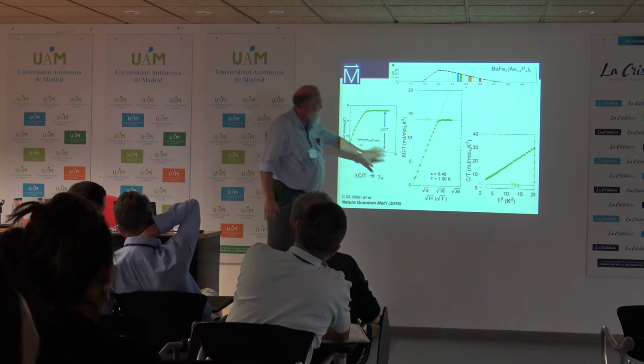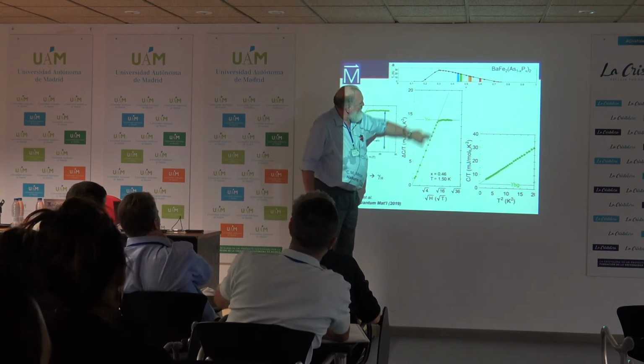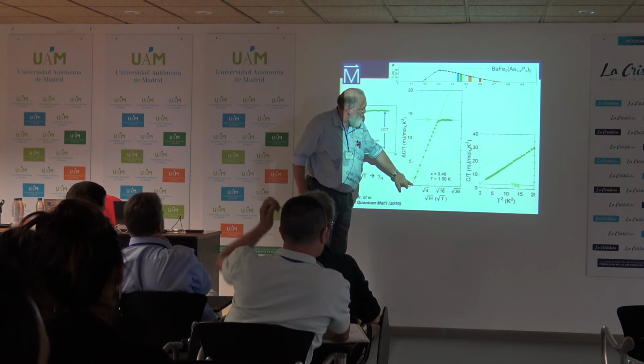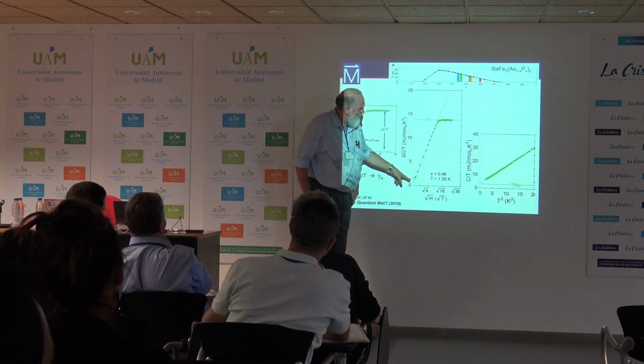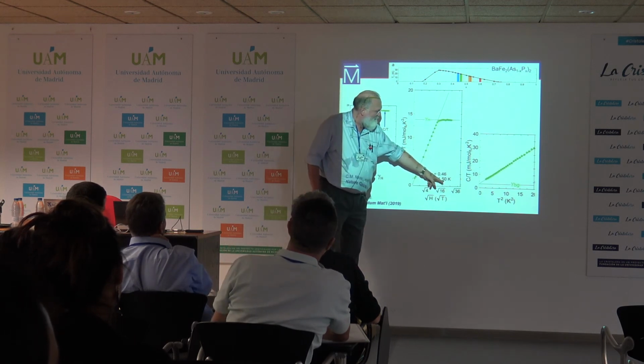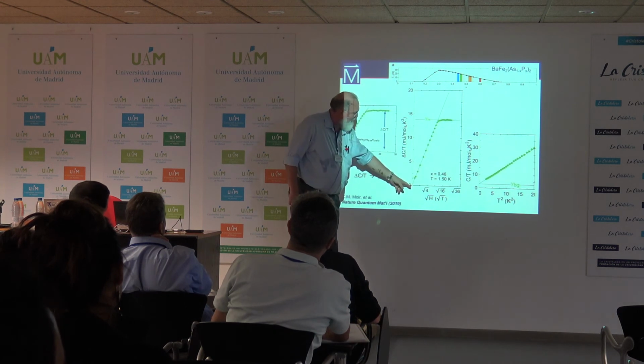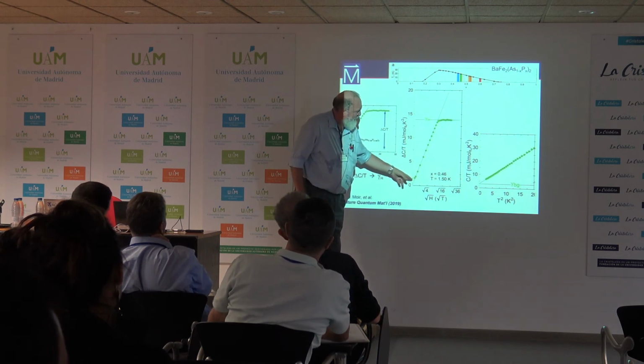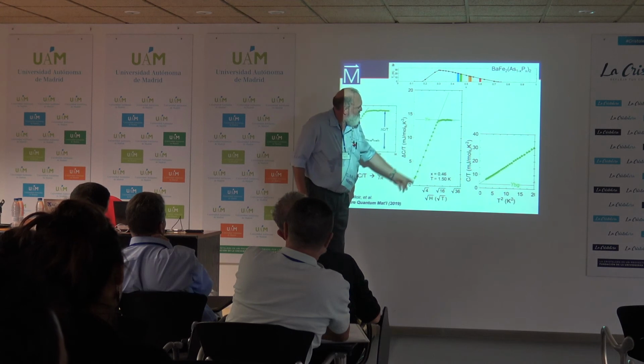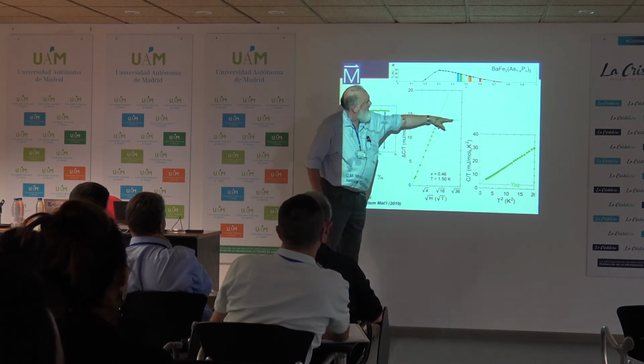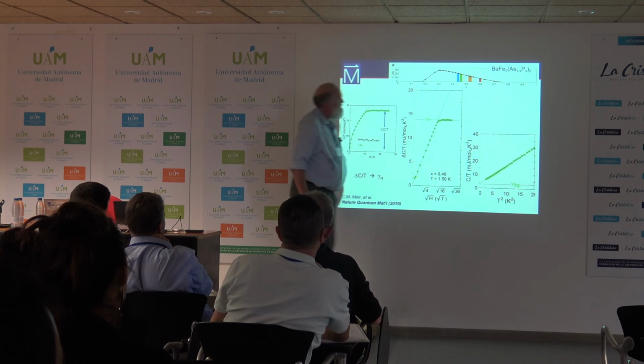If we take that same data and plot versus square root of H, you can see this very nice linear behavior on square root of H. There's some finite temperature effects because we're measuring at 1.5 Kelvin, and your gap's dropping to 0 here. So you've got some thermal excitations across the gap, but this is the region where you've got a superconducting phase. This is the region where you're in the normal state.